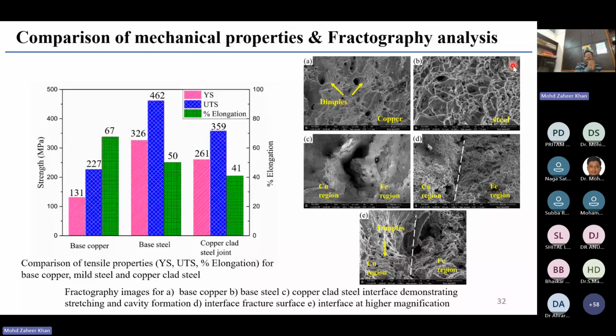This is more detail of the tensile test specimen. As you can see, the base steel has a UTS of 462. The base copper has a UTS of 227, and our copper cladded steel has a UTS of 359, which is very close to steel, and very much in between the strength obtained in pure copper and steel. Similarly, the yield strength is also lying in between.